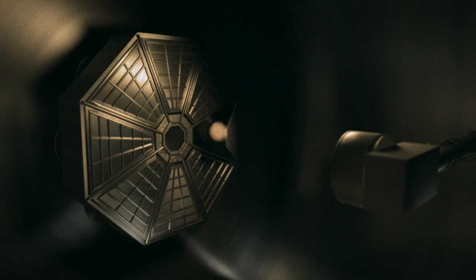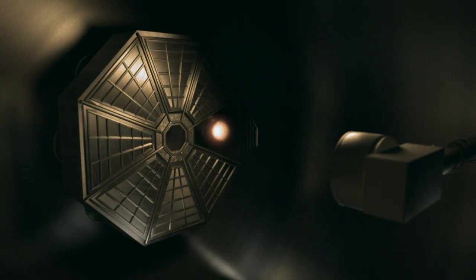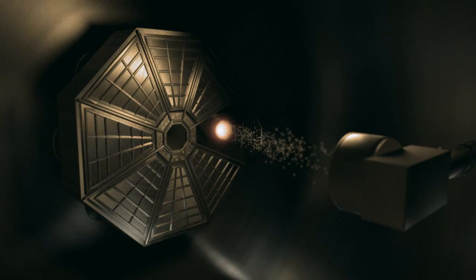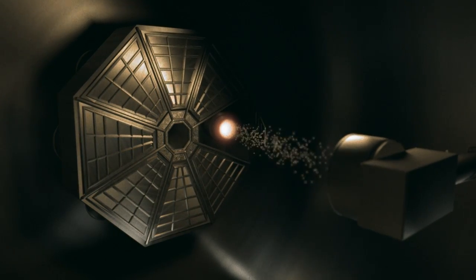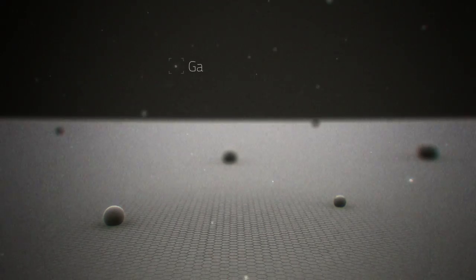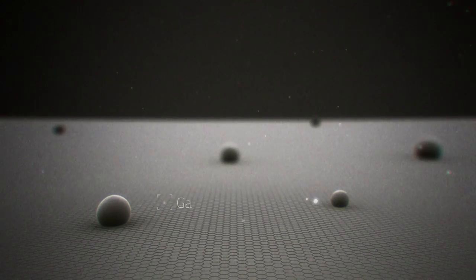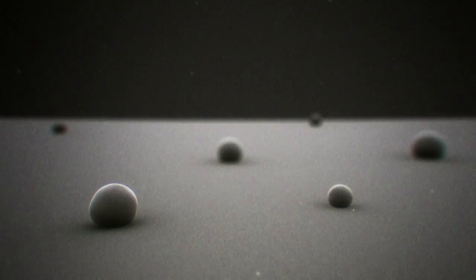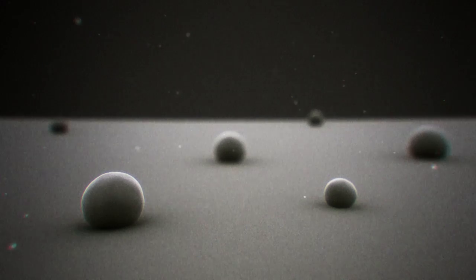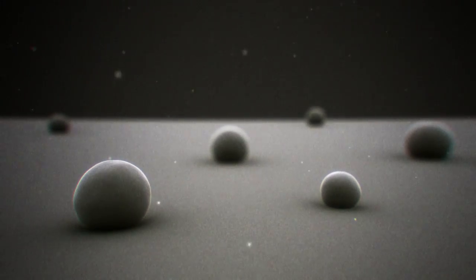Here, inside the MBE chamber, we first open the flange to the heated gallium source so that an atomic flux of gallium atoms is directed and then adsorbed on the substrate, which in our case is an atomic thin sheet of graphene. Here we see how the gallium atoms adsorb on the graphene surface. It turns out that the gallium atoms tend to stick to each other and form small gallium droplets on the graphene surface.